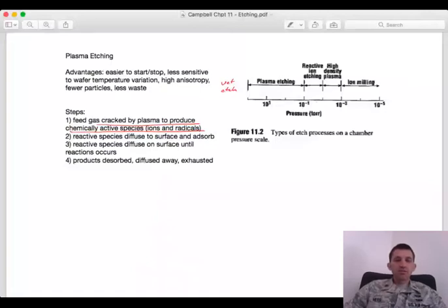Sometimes the products form as a gas, and that gives you a gas that forms on the surface, and that forms a barrier, right? If you have a bubble there, that slows the etch because now the other etch chemicals cannot get to the surface. And that could form a defect, where that bubble is, because now you're not etching away that material that you should be.